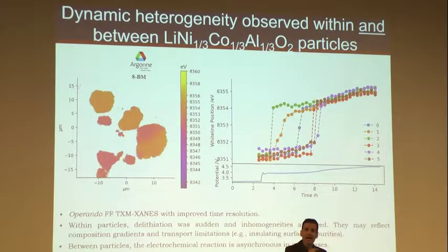And then compare how nickel gets oxidized with respect to the signal of the cell and with respect to the other particles. So this plot on the right, what it's showing is the cell being charged. And when you charge it, your potential goes up. You're removing lithium. But you're removing lithium from anywhere in the cell. And we're only imaging, what, 6 particles? There's many more in that cell. So those are not the only ones that could be contributing charge. The interesting thing is that when you remove lithium, these particular particles didn't seem to do much until a critical point, and then they just jumped.